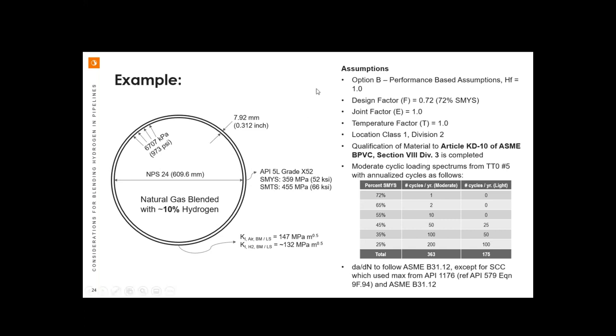Some of the other assumptions that we'll have to make here: we want to take some guidance from ASME B31.12. We want to carry out a similar type of analysis to option B, where we do a performance-based evaluation. Here are some design factors: 72% SMYS, and a line, joint, and temperature factor of 1. And really, we're just looking at a pipe that is not near any high consequence areas, a Class 1 Division 2 location. We'll look at the metal loss, dent, and crack under pretty much this sort of operating scenario where we may have moderate cycling, and then there's a summary table comparing to light cycling.